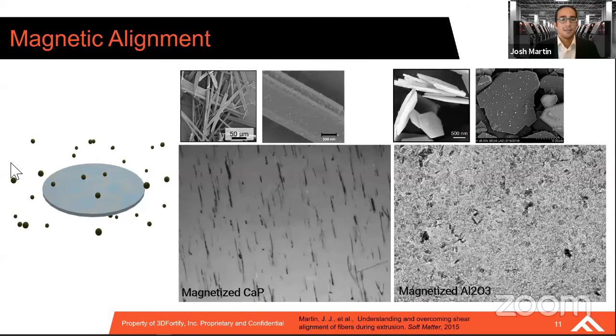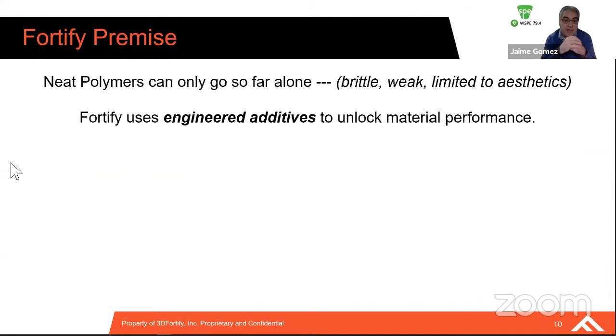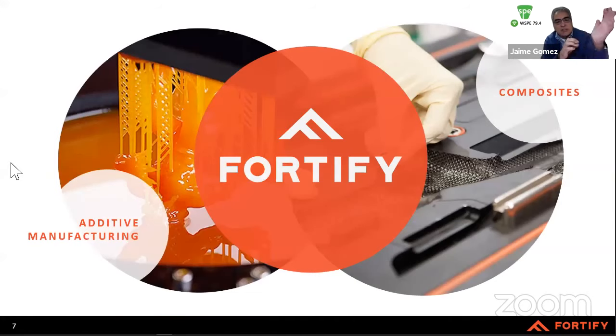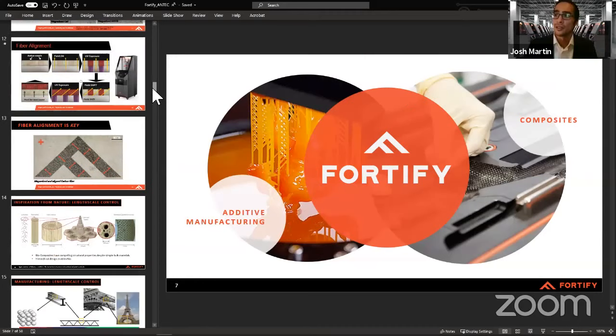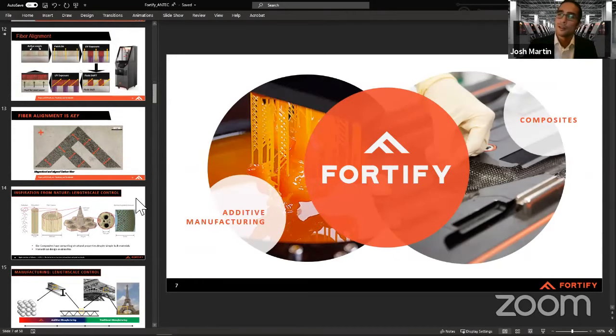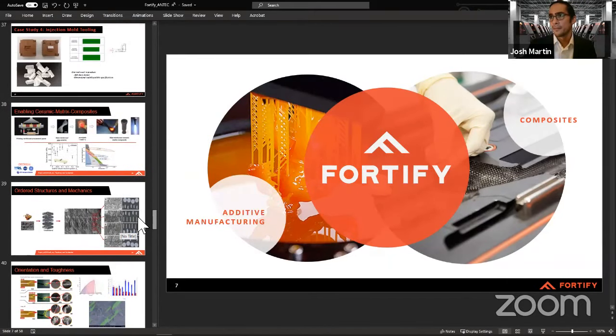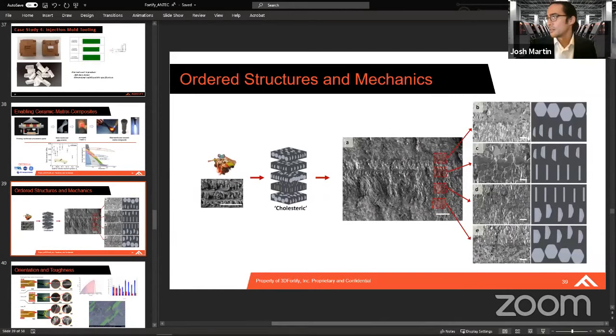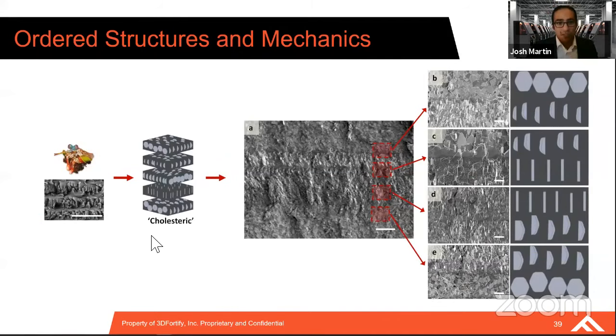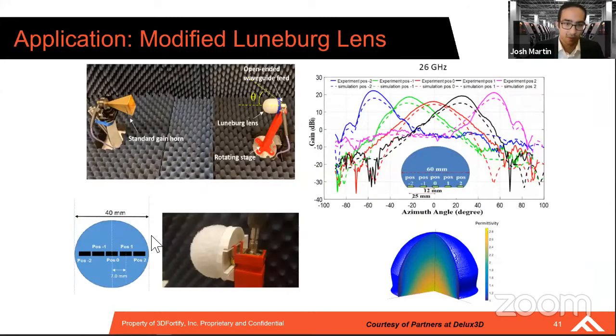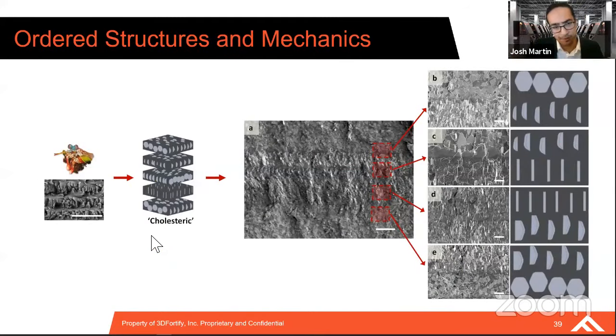Sure. But let's go back to, you were showing some CNC machines, so you were talking about different axes. Do you see any improvement in Z direction tensile properties compared to other 3D printing technologies? We do, actually. Let me see where this data is in here. I put this slide in here to show that by using what's called a cholesteric orientation, in other words, every layer has a unique pattern to it, we are able to improve the strength in the Z direction, which is interesting. We're able to drive it up by about 30 to 35%.